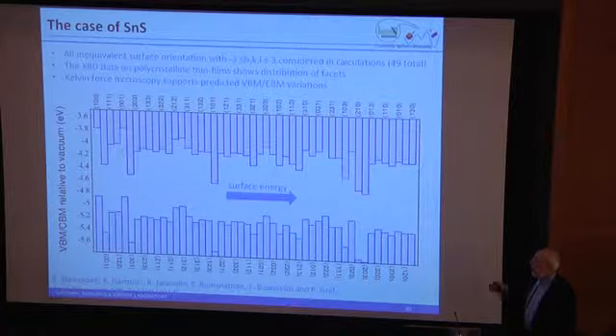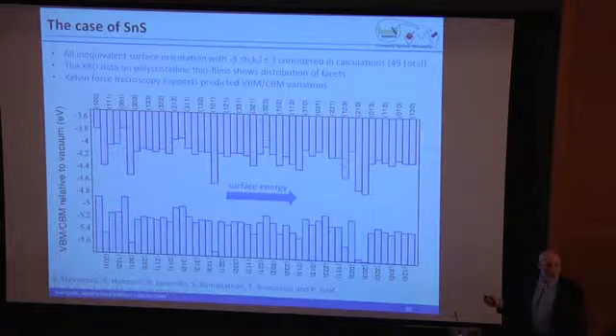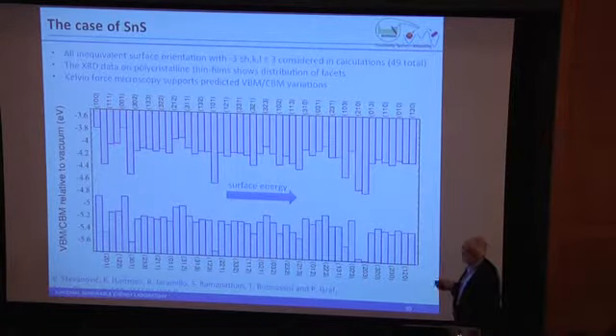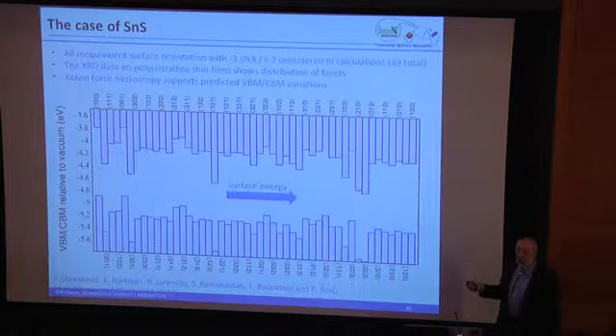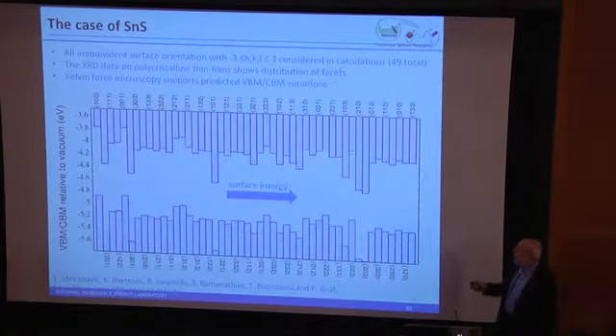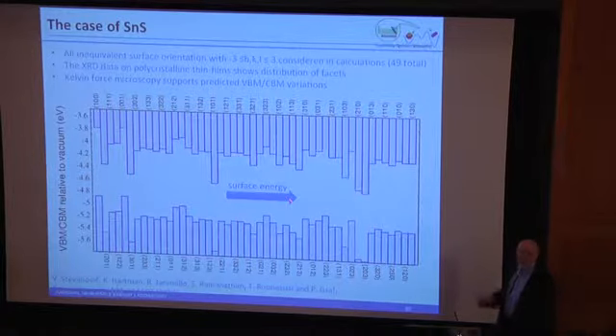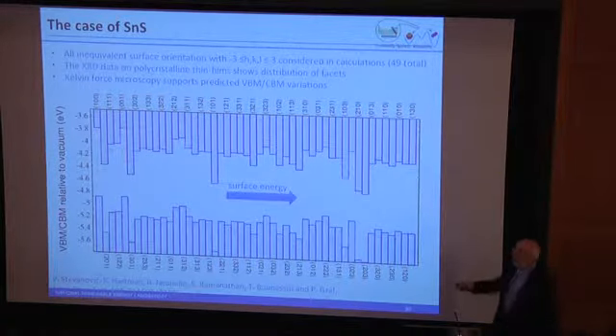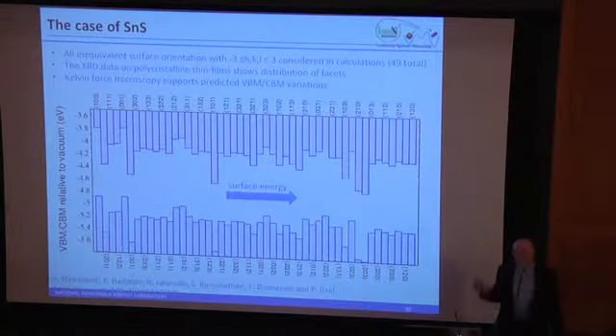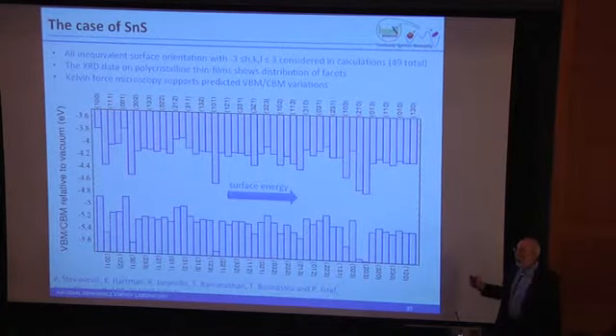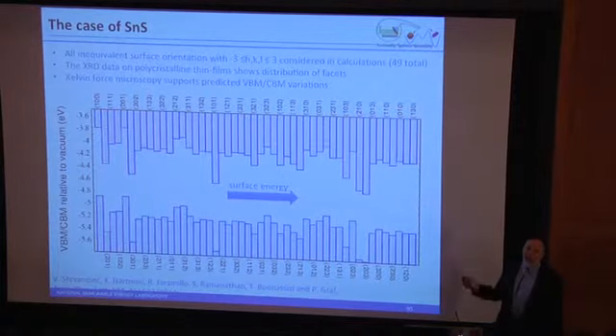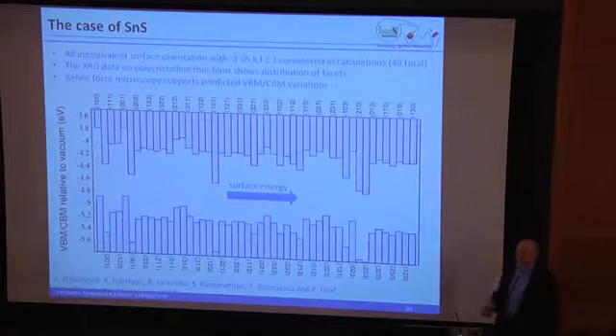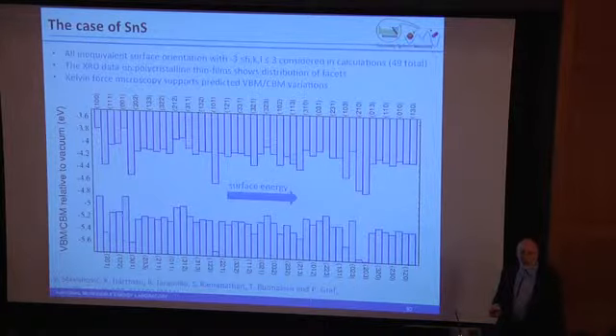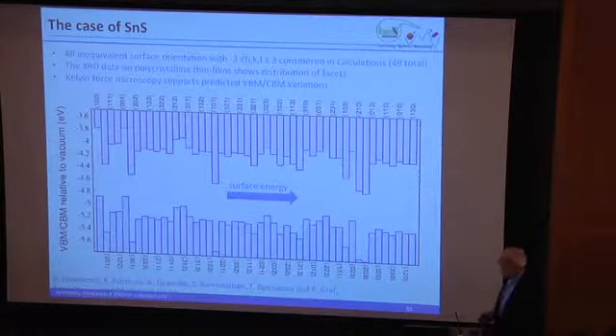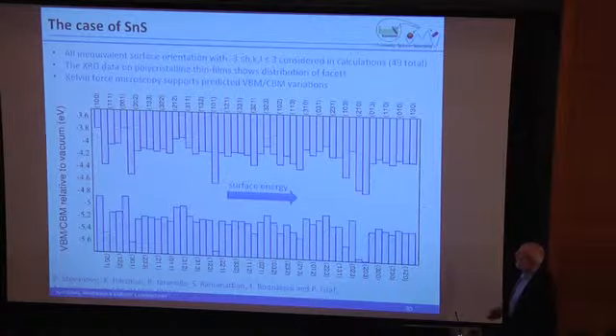And I think this is illustrative of what we see for pretty much any material. What it tells you is that we really have to start understanding, and we don't yet, computationally, why when we make a polycrystalline material, we get a set of particular orientations. We don't get an average of all of these. We get particular orientations depending on how we grow the material. And so how to derive that so we know what these energies are is one of the challenges that we don't have the answer to right yet. But this does show you how important it is.